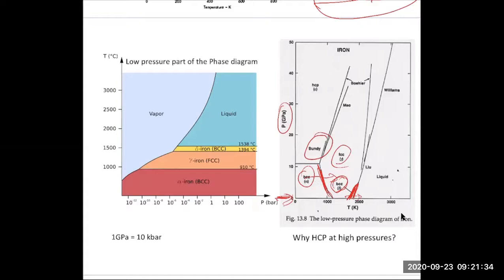Because what is dG/dP? It's V, right? So what I'm saying here is that the phase with the smallest volume gets the least free energy increase with pressure. So that's going to become more favorable, and FCC is closer packed than BCC. So FCC wins over BCC, right? The BCC field gets smaller, this one even disappears, and FCC gets bigger.